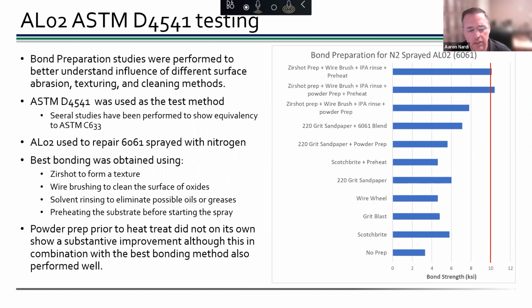And you can see here that all the way from the bottom here, which had no surface prep at all, and so this is a 6061 plate as rolled, as delivered. Did Scotch-Brite, grit blast, wire wheel, sandpaper, all the way up. And you could see that getting to that 10 KSI sort of strength, which is right where we want to be, you're doing a fairly substantial amount of surface prep with peening and wire brush and of course IPA rinses and even a little bit of preheating. So running the torch over the part a couple times before you start to spray. So this is very good information, and this is of course nitrogen sprayed 6061 based material.